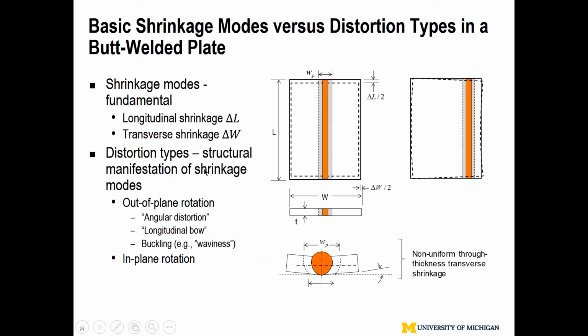If no other phenomena are involved and the weld position is symmetric, meaning left and right have the same area, then for a thin plate you only have shrinkage. As long as the penetration, the fusion, and the plastic zone are symmetric with respect to the weld center, you are not talking about distortion, but simple shrinkage. That shrinkage is very minimal.